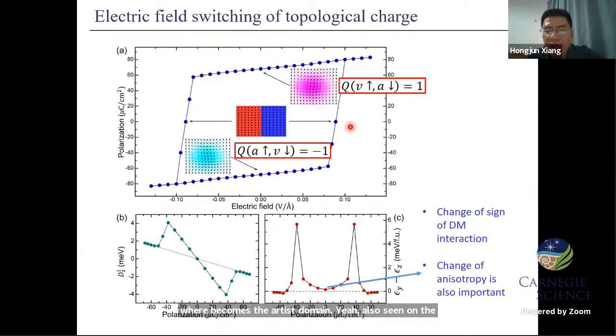So we found that we can switch this one, and the spin direction along the Z axis will not change. Under the electric field, it changes the anti-vortex to vortex, and the vortex to anti-vortex, and at the same time the topological charge changes from -1 to +1. This mechanism needs several effects. First, we need to change the Dzyaloshinskii-Moriya interaction, and the change in anisotropy is also important. This will keep the spin direction along the Z axis.